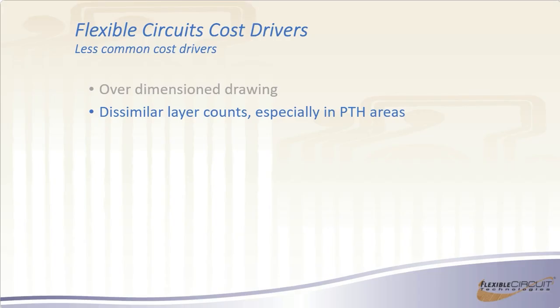Dissimilar layer counts. This is typically on rigid flex or multi-layers. I do have customers that will sometimes say I need a rigid flex, and it's 8 layers, and I have 3 individual hardboard areas, but I only need 8 layers in one of those hardboard areas. Can I save some money if I only put 6 layers in the other areas? And I said, well, it's going to change the cost, but not the direction you want it to go. You want to have every area that is rigidized to have the same number of layers. We can eliminate flex layers that jump between them without a lot of fanfare. But in the actual rigid areas, because of the way rigid flex are processed, you want to make sure that even if you don't have circuitry on those extra layers, just put pads in. But you want to have the same exact layer count and stack up in each of those rigid areas.